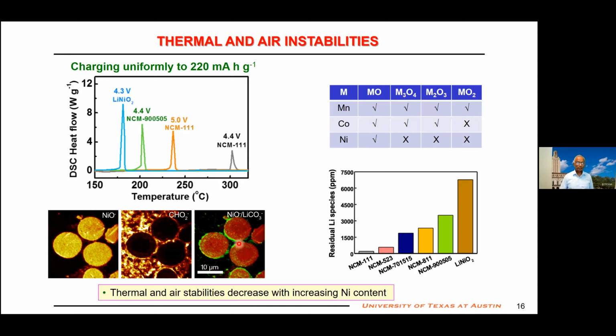The third problem is when we make this material and store it, tons of material, that's what the chemical companies have to do. If we keep it in air, they form lithium hydroxide and lithium carbonate on the surface. The green one here is the lithium carbonate and lithium hydroxide on the surface, again with time of flight secondary ion mass spectrometry. So when you store it, lithium diffuses from the bulk to the surface to form these, because nickel 3+ is not very stable. We can understand that from very basic chemistry. If you take manganese, we have MnO, Mn3O4, Mn2O3, MnO2. Very stable, no problem.